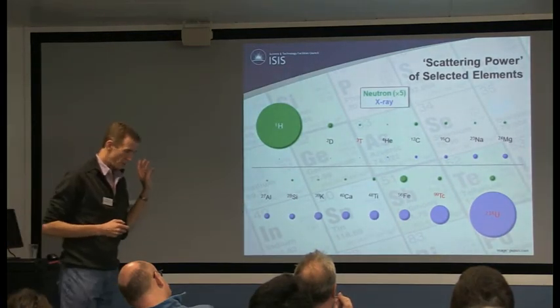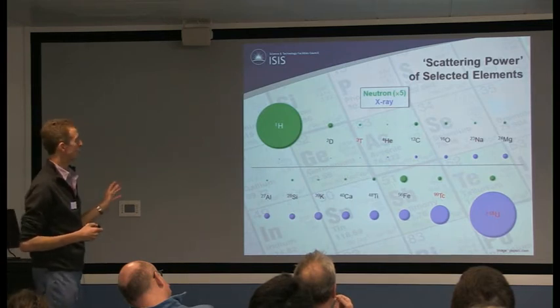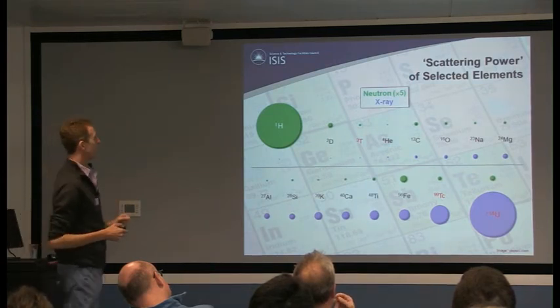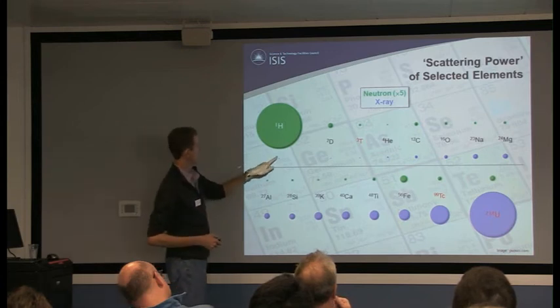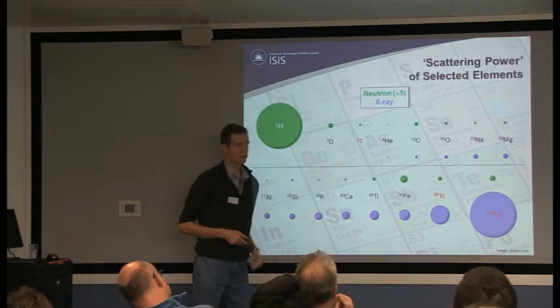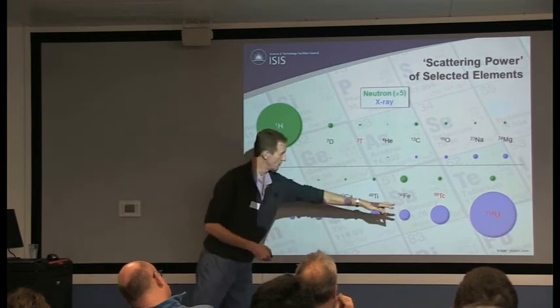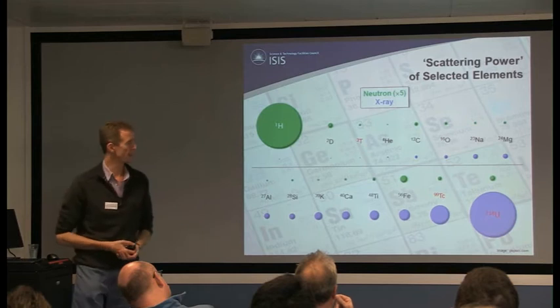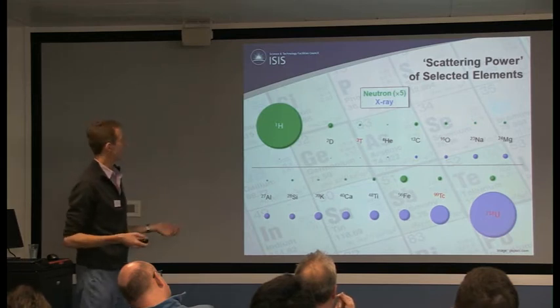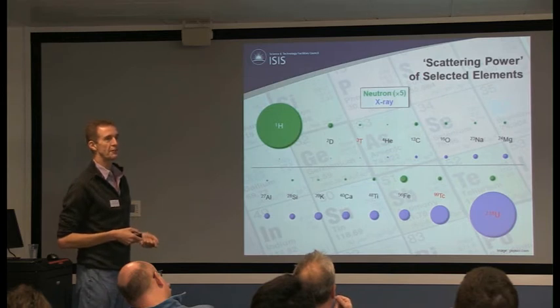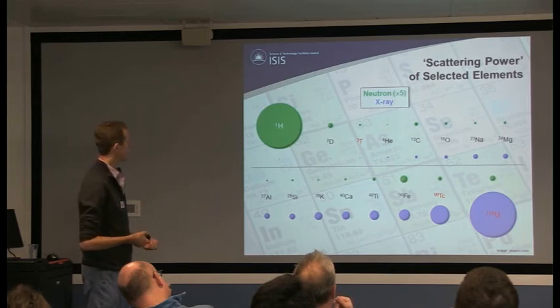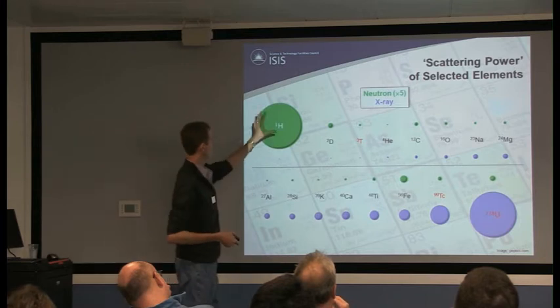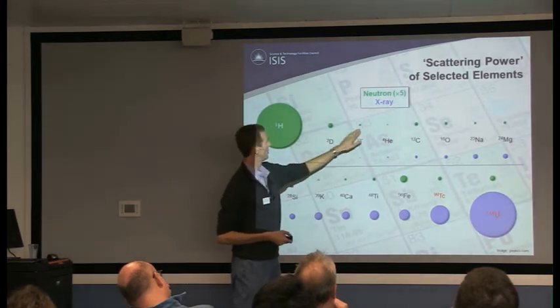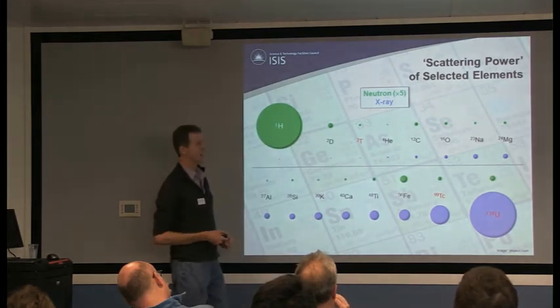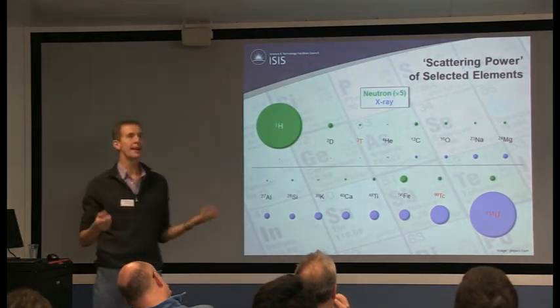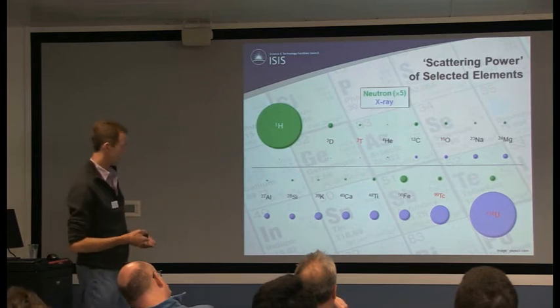This is reinforcing what I was saying about the difference in the mechanism of interaction between neutrons and X-rays. For the X-rays, you're looking at the blue dots. For hydrogen, deuterium and tritium, X-rays really don't see them very well at all, but X-rays are very good at looking at the high atomic number elements. In the case of neutrons, I've had to actually blow up the cross sections by a factor of 5 to put them on the same scale here. You can see that with the exception of something like normal hydrogen, you have this rather irregular variation in the scattering power across the periodic table, and that's what allows you to look at heavy and light elements together in a material.